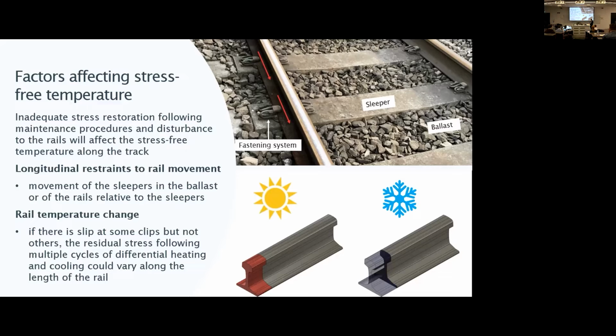And the second factor is the rail temperature change, so daily and seasonal variation in the temperature. If there is a slip at some clips, but not others, the residual stress following multiple cycles of differential heating and cooling could vary along the length of the rail, and thus the longitudinal movement. The rail temperature can change with the daily change of the temperature, depending on the track location, so a part of the track located, let's say, in the sun and part in the shade. And if the fastening system is not adequate, the stress can transfer from the hot part of the rail to the part of the rail in the shade.